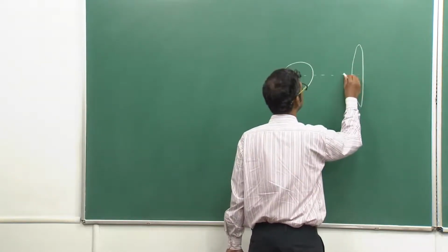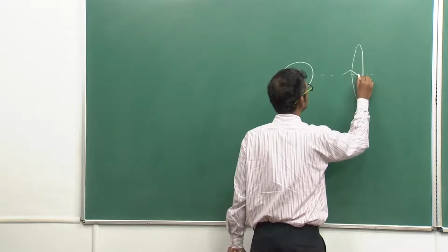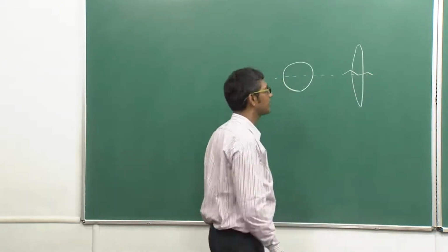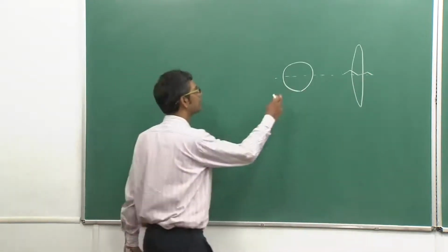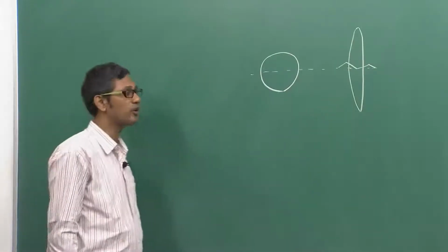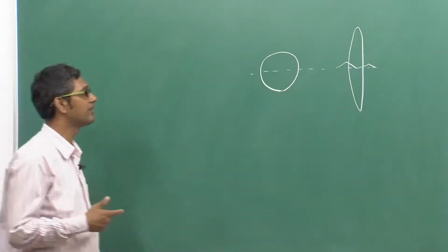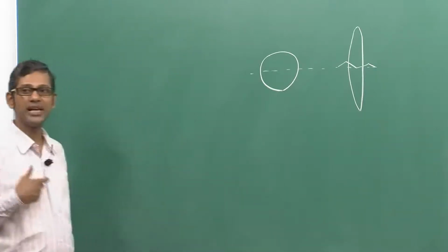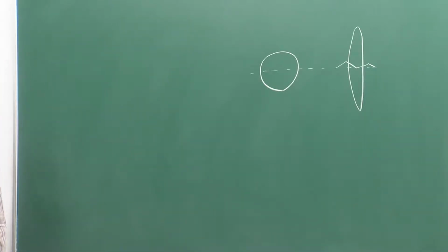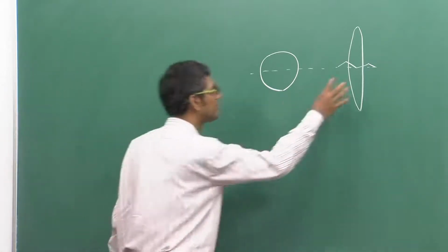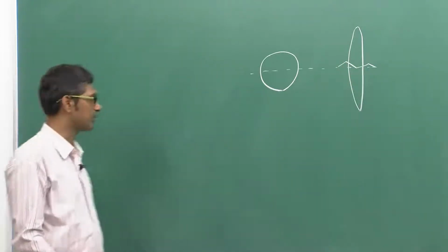Okay, we can do the twinning this way to show that. So the distortion of these to these is accompanied by a twin, and this means that twinning leads to a lot of defects inside the martensite. So if this has to be a crystallographically important feature, the nucleation process must take care of the distortion process.